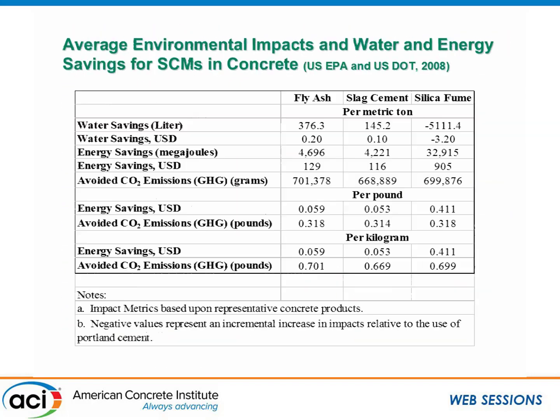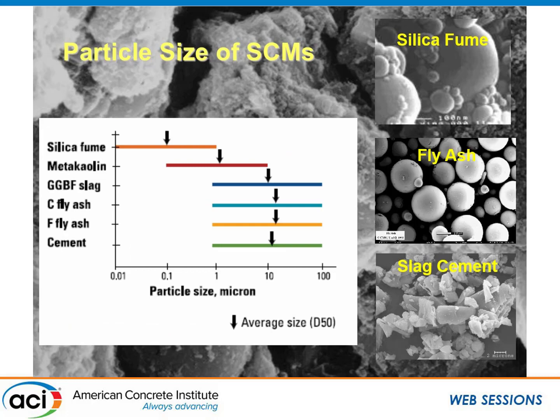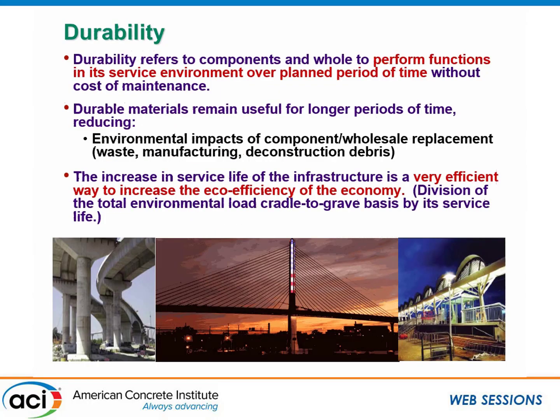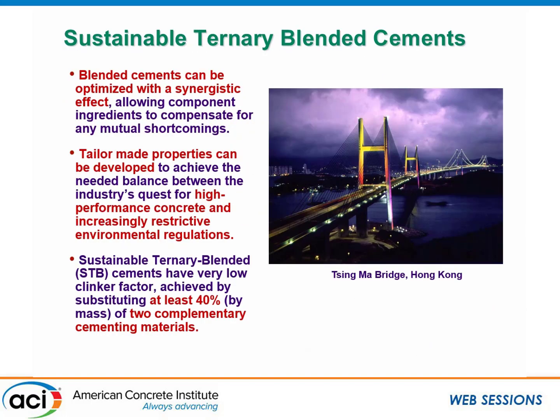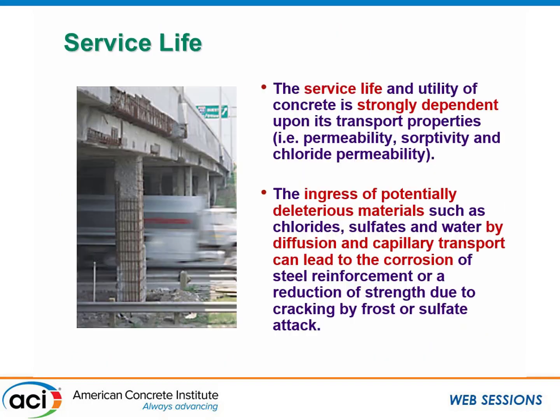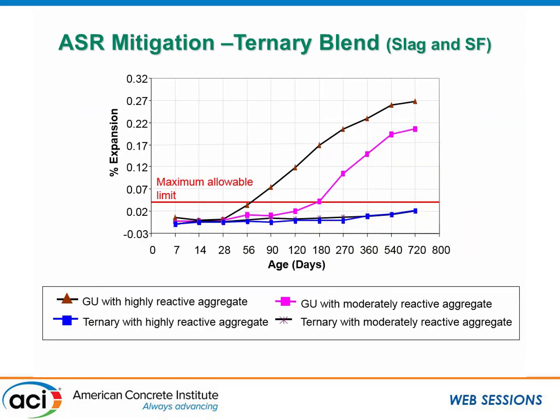Just in closing, I'm going to go through a few slides at the very end to cover what Sabby was talking about. It is the durability, the ability to perform your function in a service environment over the planned period of time. And we can do this very effectively when we use blended cements. And certainly here's some data that discusses that when we used a ternary blend. In this ternary blend, we were using between 4 and 6% of silica fume and anywhere between 45 and 55% of slag cement, looking at how it's going to have impact on the durability characteristics.